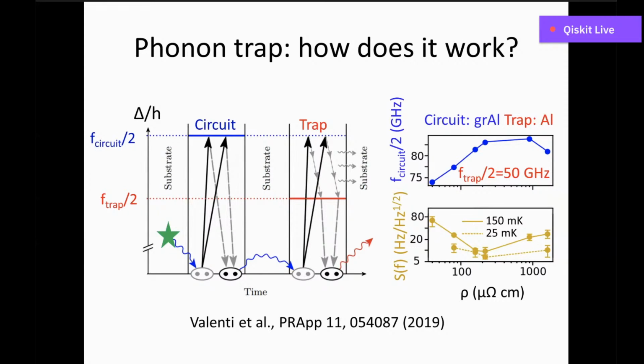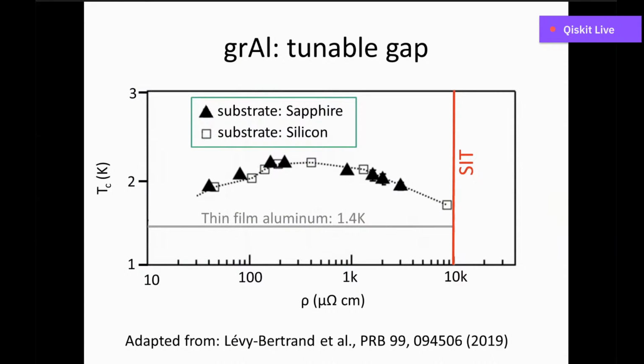Yes? Francesco, how do you measure the gap of the circuit over 2? We do it in two ways. We can extract the critical temperature, or we can directly measure the gap from terahertz absorption. Do you have the ability to do that direct measurement with terahertz? We do this with a Martin-Puplett interferometer. This technique is detailed, if I may go back some slides, in this article that I show at the bottom. Thank you.